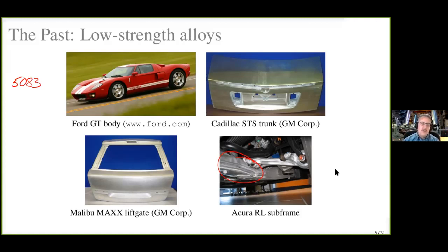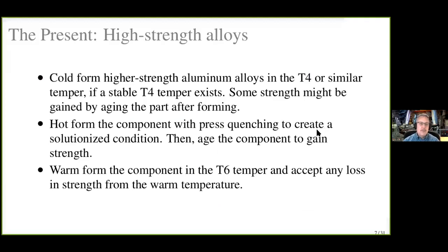Well, we could still use this technology, and it is used. But if we want to introduce high strength alloys, we basically have the following state of affairs that's available for current production and that's in development. The first is to try cold forming. So we can cold form some of these materials if we can get a stable T4 temper. We'll review for you. The T4 temper for aluminum is the temper you have after you solutionize and quench. So all the alloying additions that we eventually want to end up in precipitates for strengthening are locked in solid solution. Now, in that case, we can have a much softer alloy than the T6 and usually get quite a bit better ductility. The problem is that for these high strength aluminum alloys, some don't have a stable T4 temper.